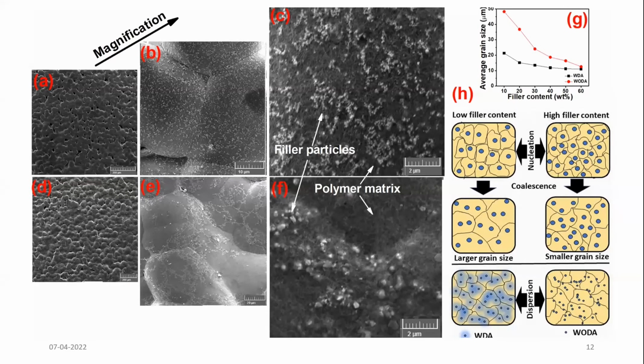And these are the SEM images. The upper ones, A, B, C, are with dopamine added, and D, E, F, the lower ones, are without dopamine added. It was seen that lower filler content gave larger grain size, and higher filler content gave smaller grain size. Here, filler content means I changed filler from 10% to 60%. So for each, like 10, 20, 30, 40, 50, for each filler the results were recorded.